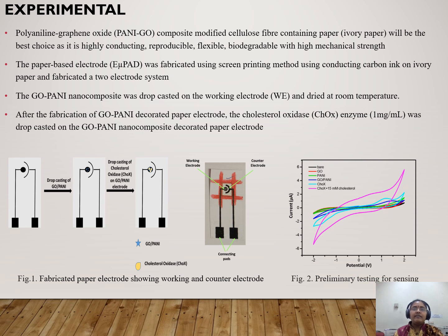For that, graphene oxide was synthesized in the lab using the modified Hummers' method, and polyaniline was procured from Sigma. The polyaniline powder and graphene oxide were both dispersed in DMSO, added together, and sonicated for a few hours so that the composite can be formed uniformly. So we got the uniform composite dispersion. Before that, we designed the sensing electrode design as shown in the figure.